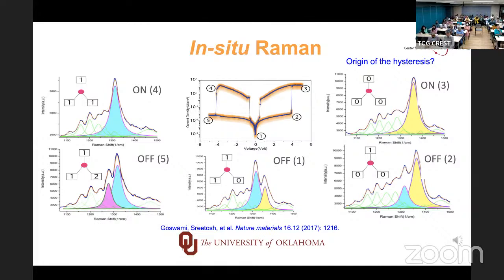Essentially, electrons hop from the bottom electrode onto a molecule, then hop from this molecule to the next molecule. But the molecular hopping is determined by the overlap of the LUMO band. If I have a non-identical ligand, the hopping will not be allowed because the LUMO band won't match. So the probability of hopping per molecule in this system is only 2/3. But the total hopping requires, say, 40 hops. 2/3 to the power of 40 becomes a very small number. That's why these are off states and these are on states.